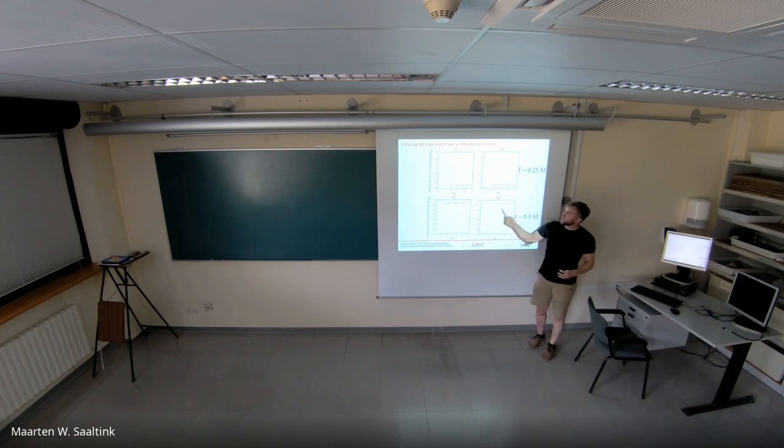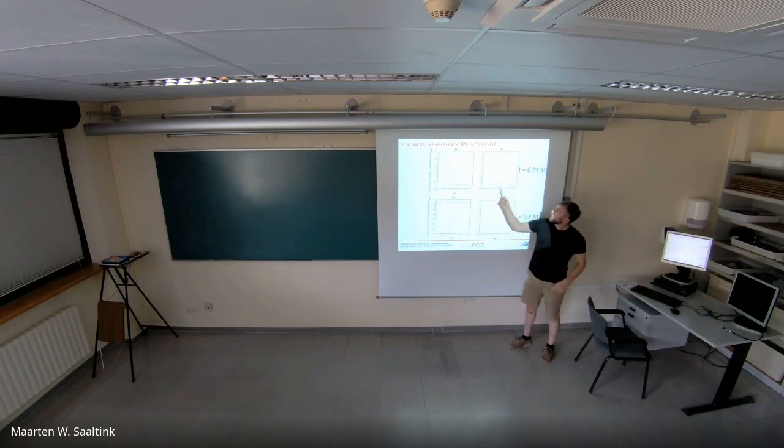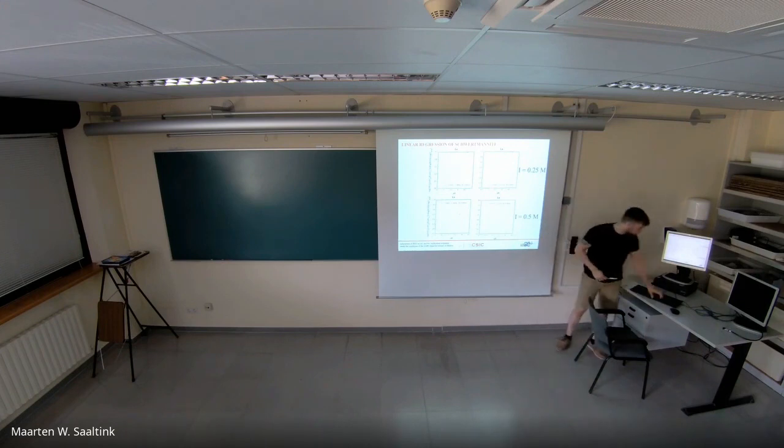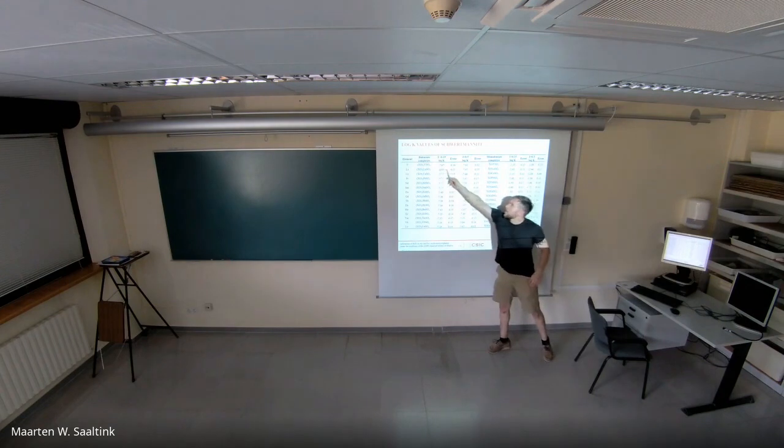So our guess would be that they are both reactions occurring on the surface of schwertmannite. In order to extract the thermodynamic data, we have to use software and force the slope to 1 or 2 to obtain the equilibrium constant for the reaction of each number of sites, each n value. These are the reactions. It's a very big table, I'm sorry.